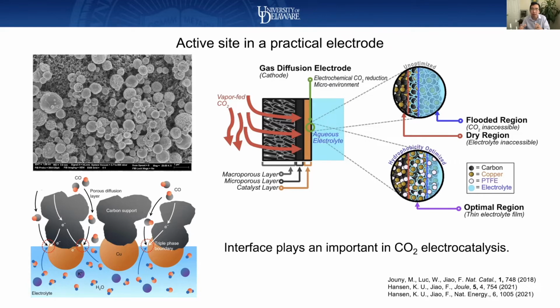If you don't design the interface or construct the interface correctly, a common phenomenon observed by many groups is called flooding. Basically, the liquid aqueous electrolyte wets the whole interface and also diffuses partially into the gas diffusion layer, blocking the CO2 diffusion to the surface of the catalyst. And the end result is you get really poor selectivity and really poor activity. Basically, you just have a lot of hydrogen production in these particular systems.